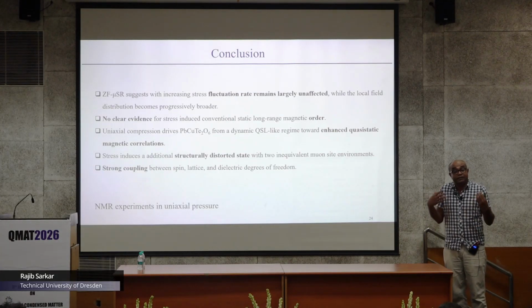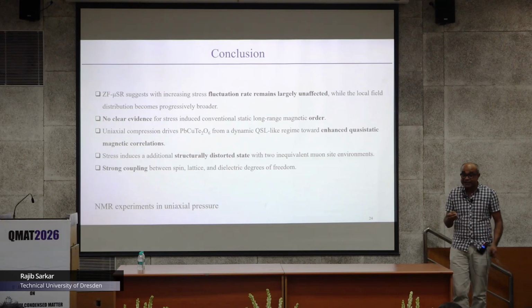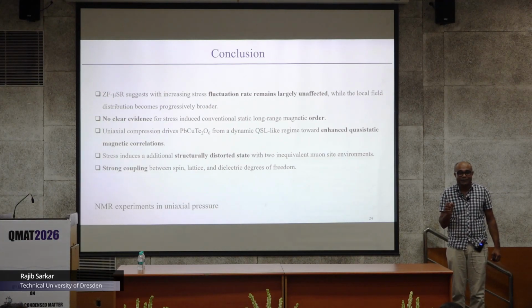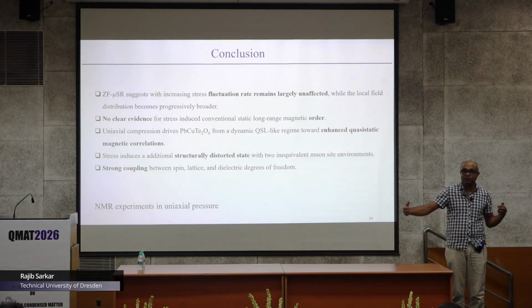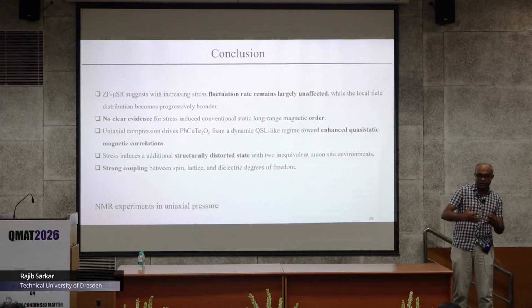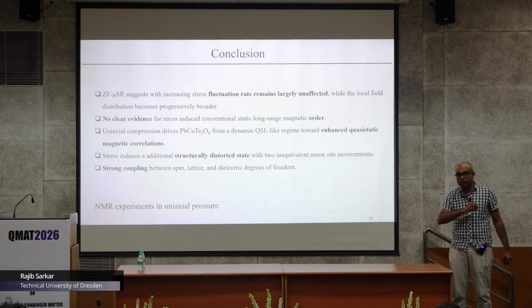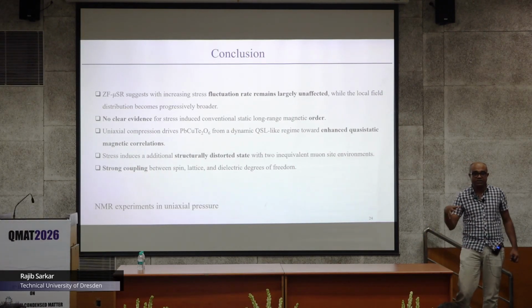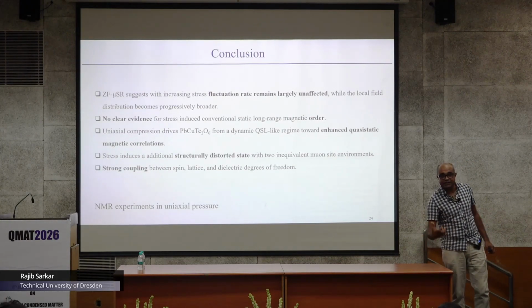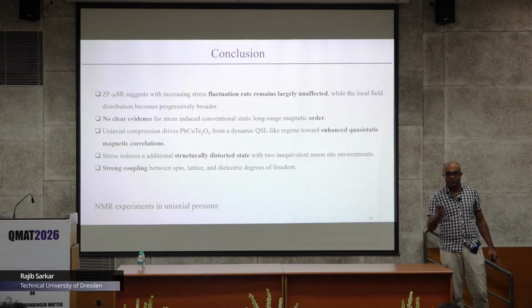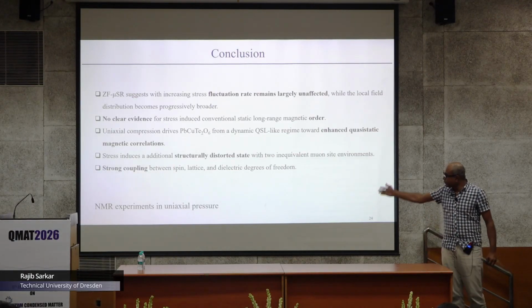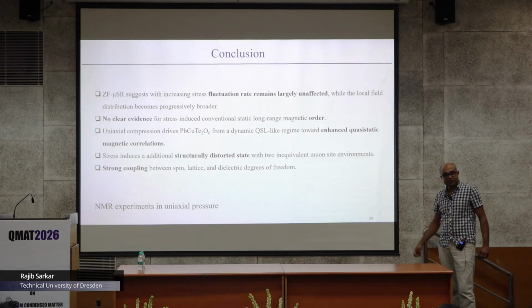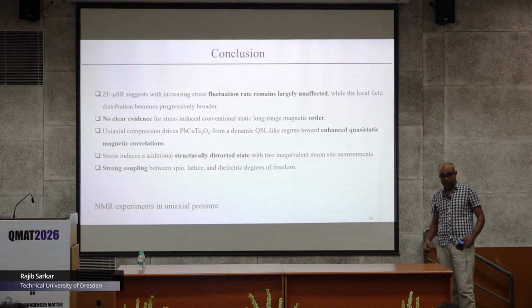Now also we are definitely hopeful that we will get solid single crystals which are sustained with this kind of pressure, and we can essentially tune from a completely disordered ground state to the ordered ground state. That means we need not dope the material or introduce additional disorder which jeopardizes our inherent physics. We can basically probe it by uniaxial strain. Of course, now our next target is to do the NMR experiments on this system under uniaxial pressure.